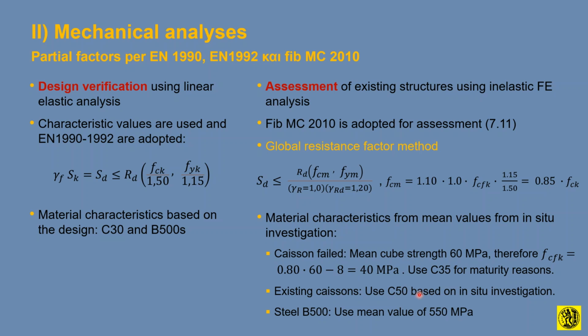But for the future caissons, the existing caissons, which were already waiting for 2 months because the project stopped, we could use much higher strength, because the in situ concrete was measured by cores now, not by cubes during construction. We cored and took samples from these caissons, and we could use, through the same process, C50. This was the appropriate strength for the future caissons. Of course, I'm not talking about those, but they were checked. They were found to be okay. They are already positioned. Plus, the project went on, so nothing happened since then.